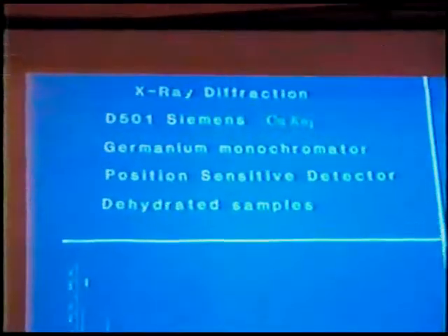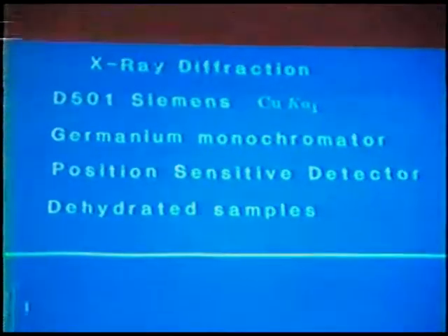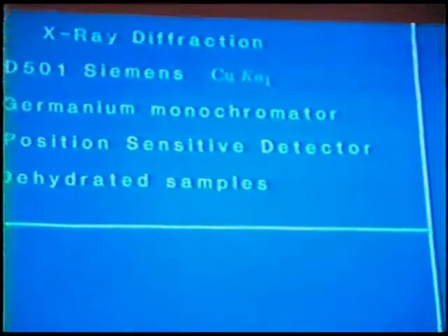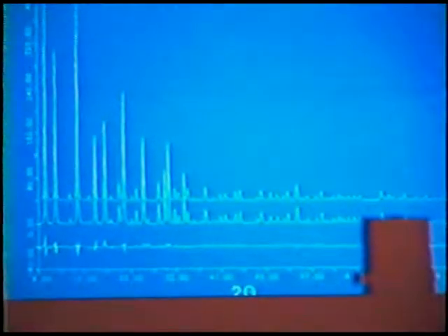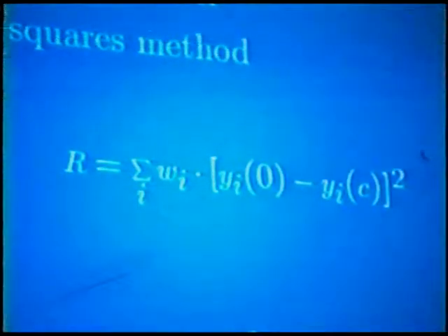On this slide, you can have some information on the X-ray diffraction and the Rietveld technique for refining the X-ray patterns. The aim of the Rietveld method is to minimize the reliability factor R, where W_I are fixed weightings, and Y_I(obs) and Y_I(calc) are, respectively, the measured and the calculated intensity. It is, as you can see, a least squares method.